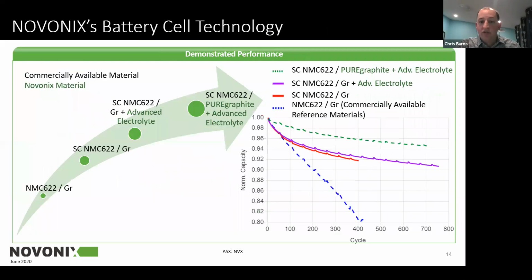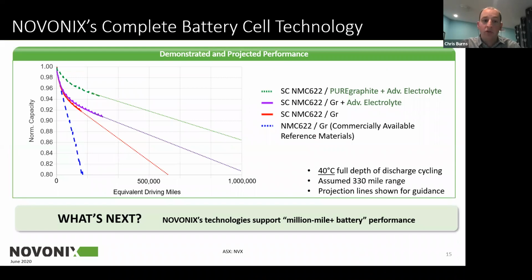And so on the previous slide, you see we're out of 700 plus cycles, and we have other cells that are out further with different technologies in them. But you can generally see the trend that these are fading on, where the commercial polycrystalline and synthetic graphite material cannot meet these type of demands at 40 degrees C to 4.3 volts. You go to the single crystal materials with graphite and you can get, let's say, 500,000 miles or more. You improve the electrolyte performance and you start to understand how these curves swoop out in time, and you're now targeting out at 1,000,000 miles.